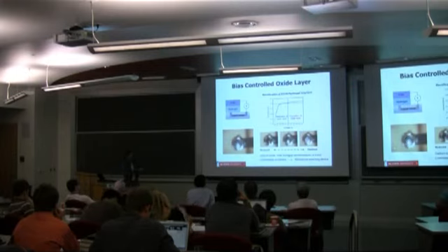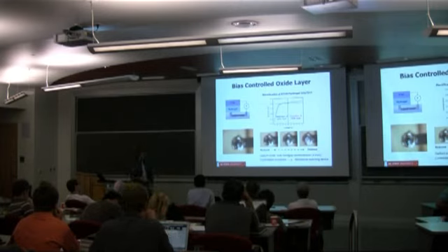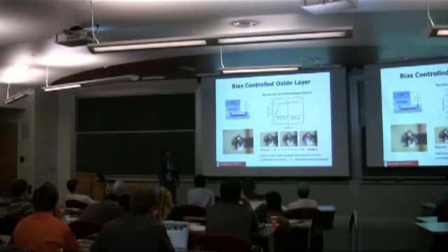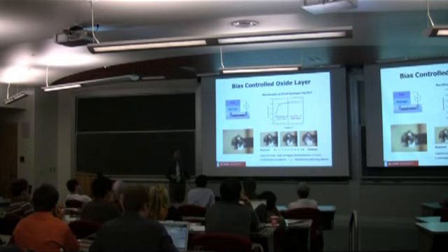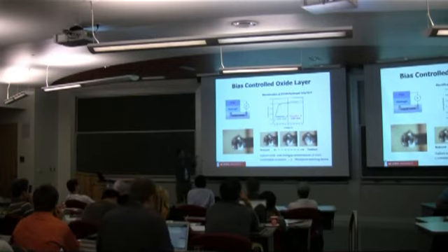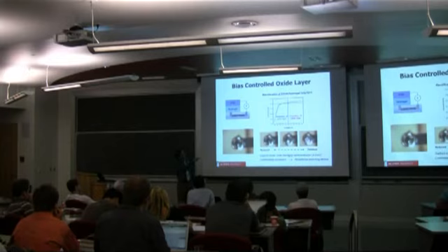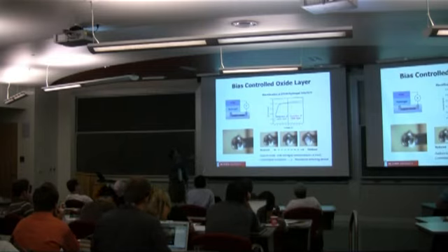Okay, so you see there's this oxide layer. We apply a potential, the oxide layer electrochemically reduces. It goes away. And so in doing that, depending on the direction of the bias we apply, we can either make the surface have this very thick and kind of gnarly looking oxide, which is a wide bandgap semiconductor, basically an insulator, or we can remove it and make it a conductor. And as a result, if you measure current versus voltage through this circuit, in the direction where we form this oxide, the current is passivating. It doesn't allow current to pass through very easily. Whereas when you go in the other direction, you remove the oxide layer and you get current. So this should be very familiar as diode-like.